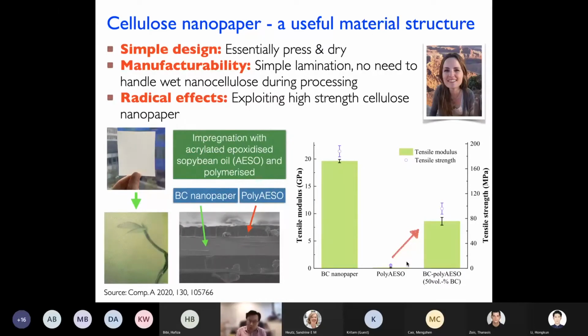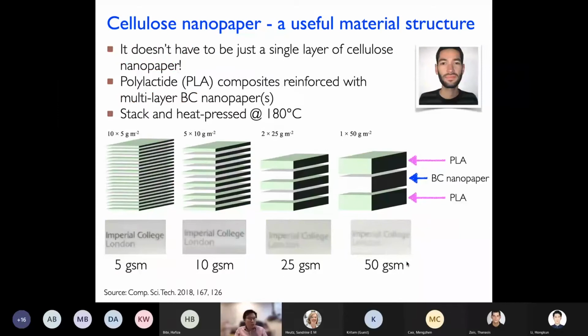And all this comes from the fact that your nanopaper is now carrying the load, and bearing in mind that the nanopaper here is the reinforcing phase, and the performance of the nanopaper comes from the performance of the nanofibers, along with the high degree of hornification in this case. Now you may wonder, well, there's only one single layer of nanopaper. It's not extremely useful there. Well, actually, you don't really need to use a single layer of nanopaper. You can actually stack multiple layers of nanopaper together to build your structure from a 100 micron thick film to a couple of millimeters thick composite structure.